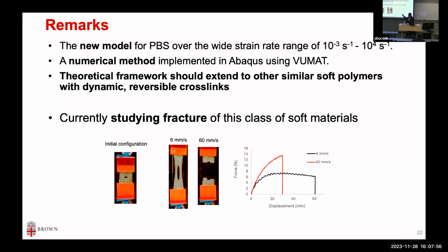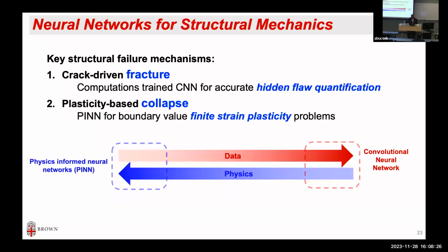So we are in the process of doing experiments and modeling this fracture, and also the self-healing following that fracture. If you look at the force deflection curve, at the low rate it can stretch a lot more, but takes only a smaller load. At high rate, it takes a larger load, but fails earlier. The area under the curve might still be the same, but more work has to be done. So a lot of interesting things are happening in this material as a function of rate dependent fracture, which I think is the next step for us to model. So more work needs to be done.